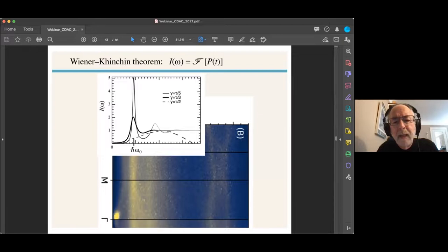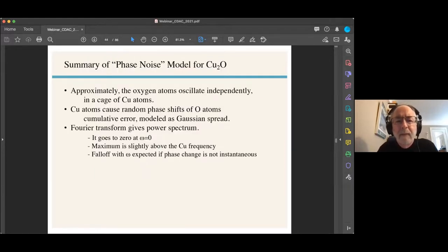And we have a shape which has a part that goes to zero, which seems to be right, and a peak here, which is very temperature dependent. I changed this phase shift by 50%, and it completely wipes out that peak. And I think that's what we're seeing in the cuprite, right? We need to do a little more on that probably to really settle it. But so far it looks like it's a change in the phase of the oxygen, which is causing the scattering at the low energies, giving us that background around the copper frequency. So it's really the oxygen doing the scattering.